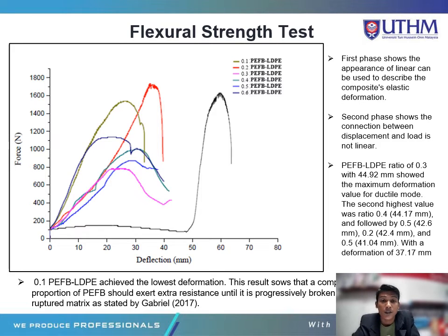This graph shows the flexural strength test. The first phase shows a linear appearance that can be used to describe the composite elastic deformation. The second phase shows the connection between displacement and load is not linear. PEFB LDPE ratio 0.3 with 44.92 mm shows the maximum deformation value for ductile mode. The second highest is ratio 0.4 with 44.17 mm, followed by ratio 0.5 with 42.6 mm, 0.2 with 42.4 mm, and 0.6 with 41.04 mm, with the deformation of 37.17 mm. 0.1 PEFB LDPE achieved the lowest deformation.